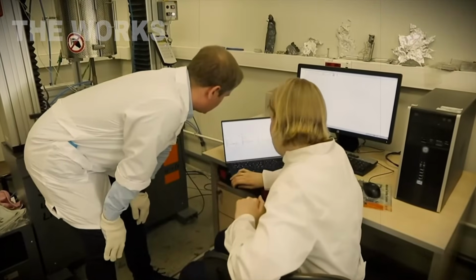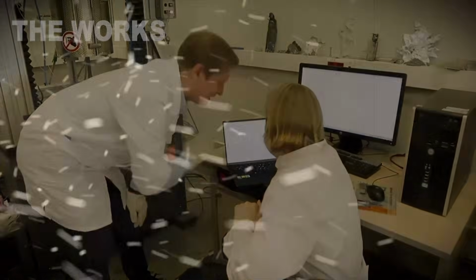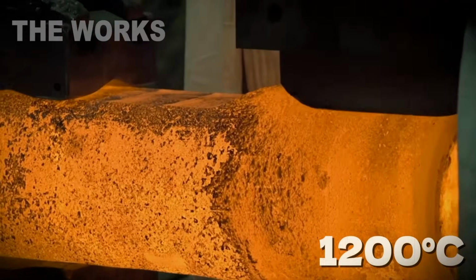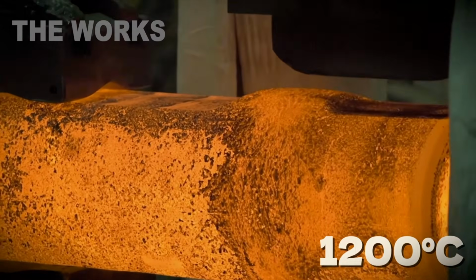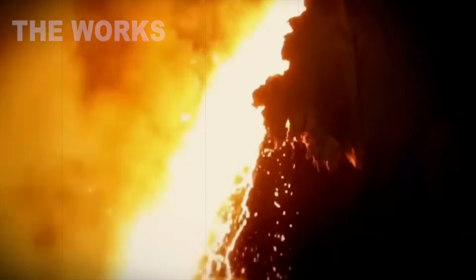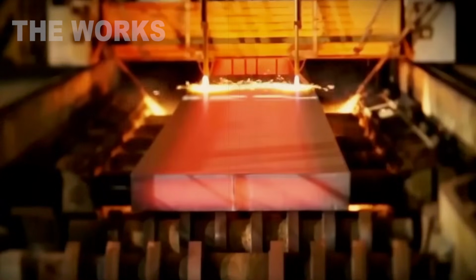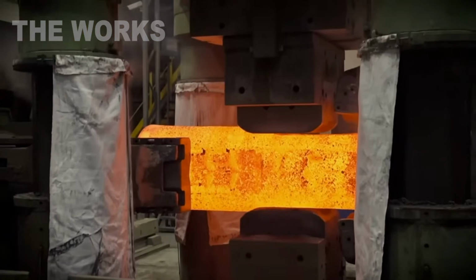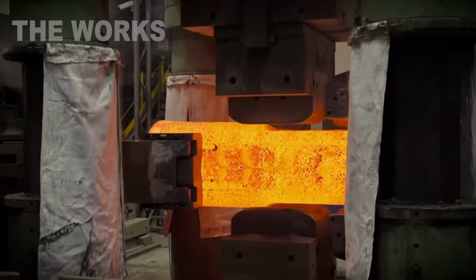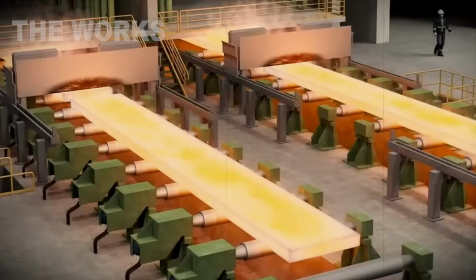Rolling and machining. Ingots are heated in a furnace to 2,200 degrees Fahrenheit. Rolled on a mill. Rollers 40 inches in diameter. Rolling force 2,000 tons. The ingot becomes rods 4 inches across. Rod length 20 feet. Rods are cut into blanks 8 inches long.